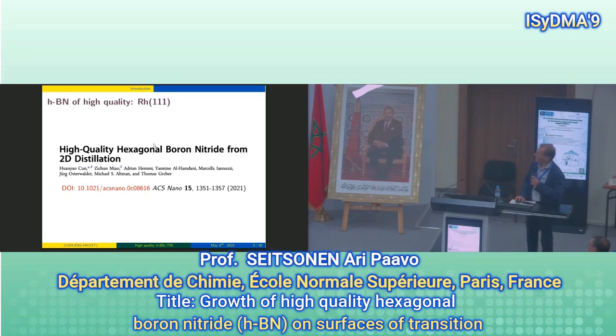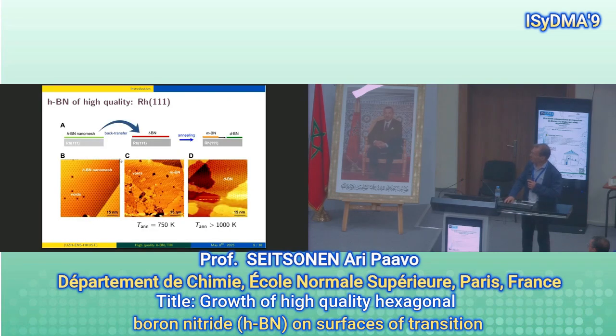This was the first demonstration of how to create hBN of high quality on a large scale and transfer it to another substrate. Because the problem is that the hBN on these transition metals still feels the electronic structure beneath. And if you want to transfer it to some other substrate, how to do it? They demonstrated this method, the so-called distillation. And I will try to go through it very quickly.